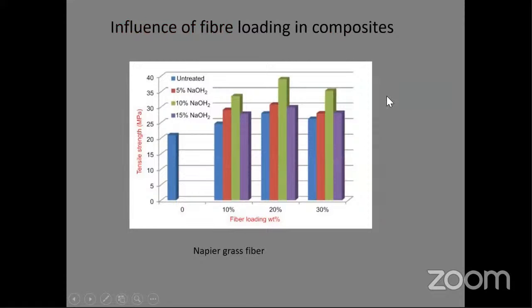And the composition: when you are increasing the compositions, how do the strengths change? When you are increasing the fiber loading, the strengths may increase sometimes, and sometimes they may decrease. Like you will see, at 10% it is increased, at 20% it is increased when compared to the pure polymers. Then after 20%, when it goes to 30%, it is decreased.